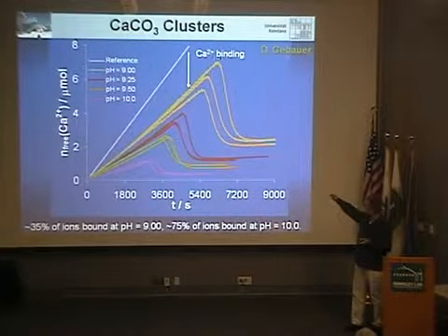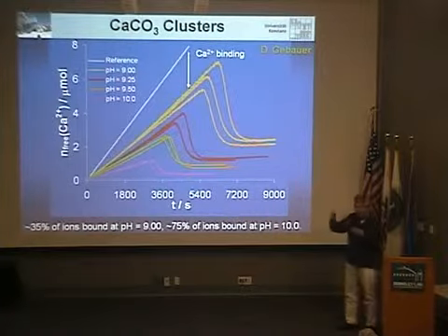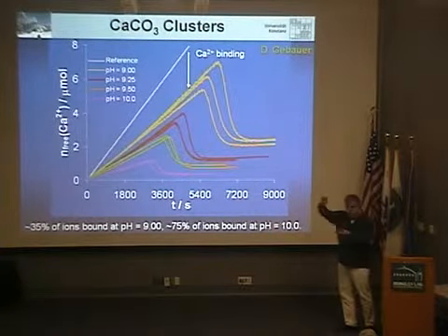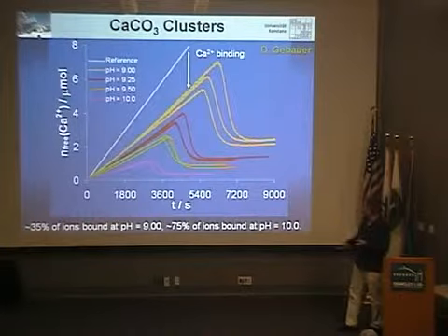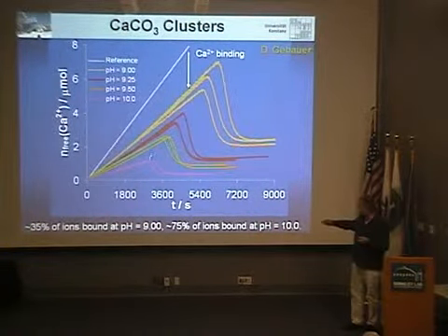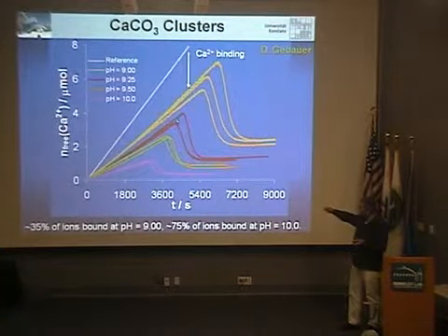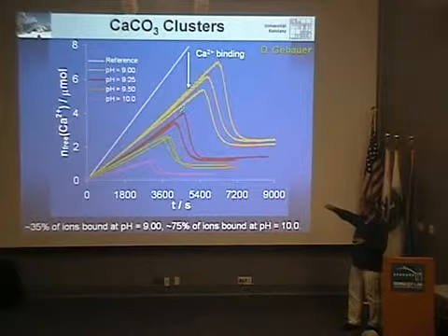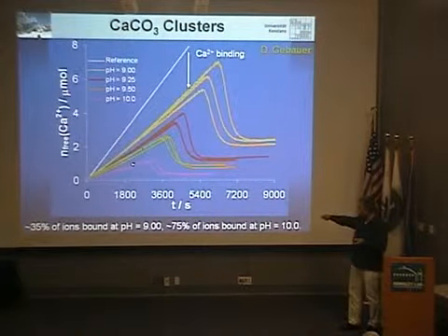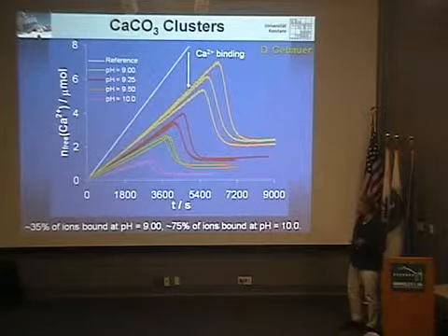And you get curves like that. So you see they are rather reproducible. The nucleation point varies, and also the supersaturation at nucleation, because that's a stochastic event, because I have to jump over an activation energy barrier to nucleate, and this is statistical. So the nucleation point is not always at the same time. But what you see is that depending on the pH, I get curves like that. And the higher the pH, the lower is the calcium concentration in solution, what I would expect because I have more carbonate and more calcium carbonate formation.